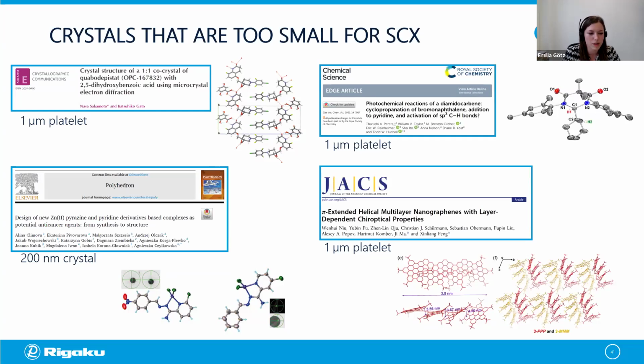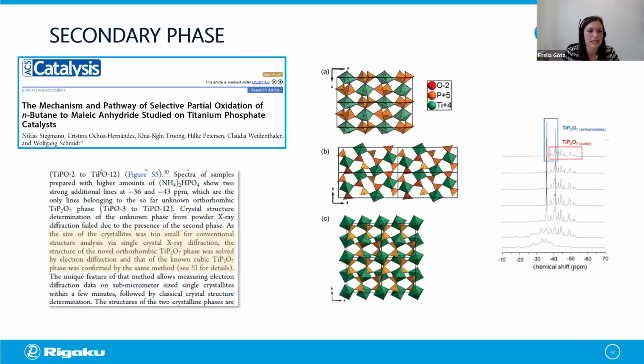In these publications by Pereira et al. and New et al., the crystals were 1 micron size platelets as well, where the thickness just wasn't sufficient for a single crystal X-ray diffraction. But as I said, sometimes it's not the crystal size that brings people to the Synergy-ED. In case of the paper by Stegmann et al., the NMR measurements clearly showed 2 titanium phosphate phases in their material, one of which was unknown.